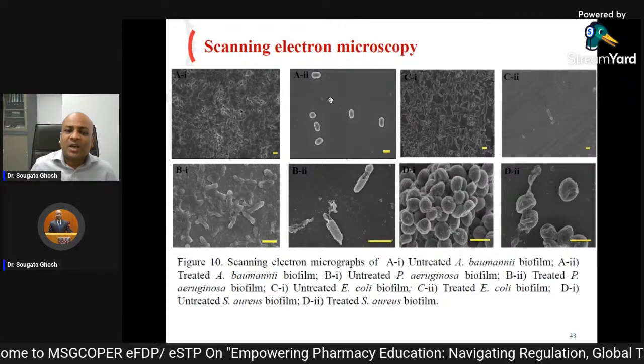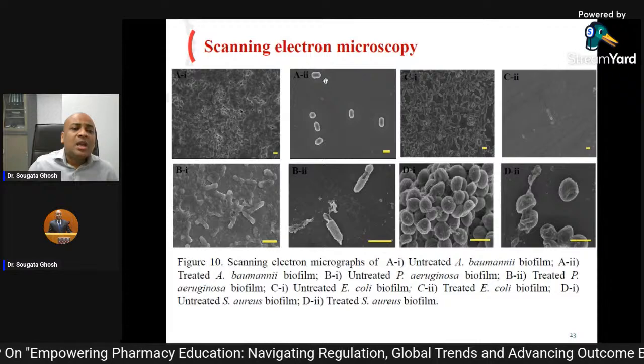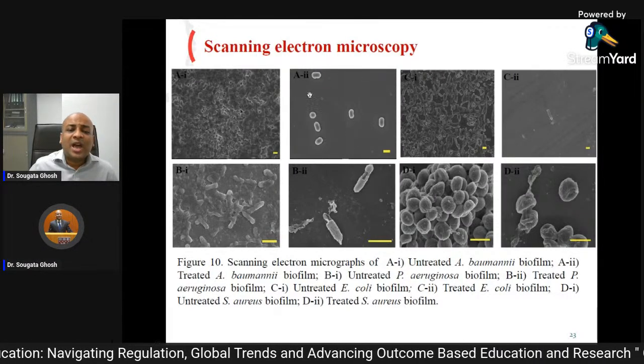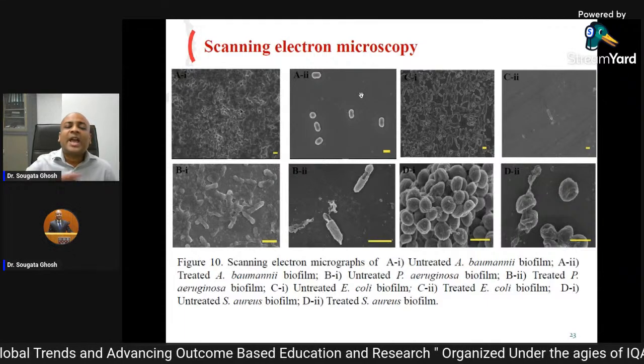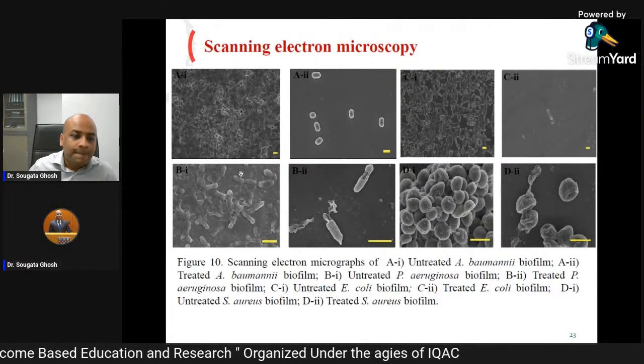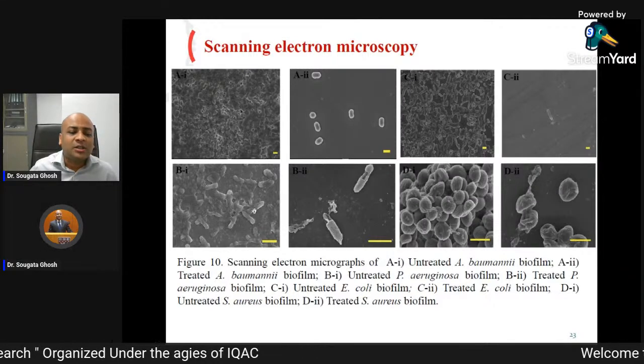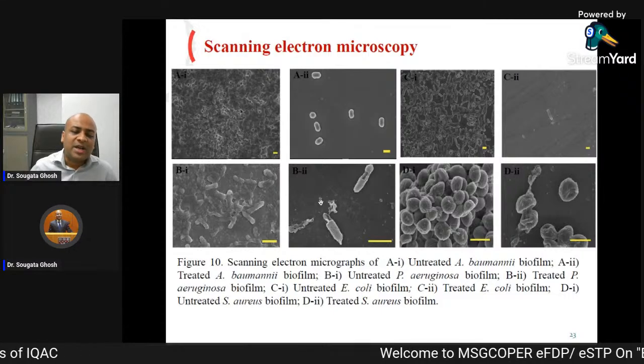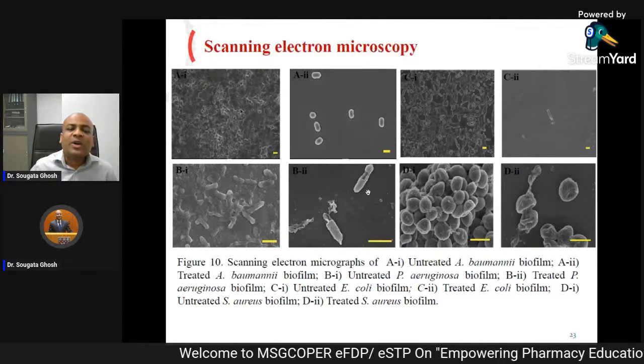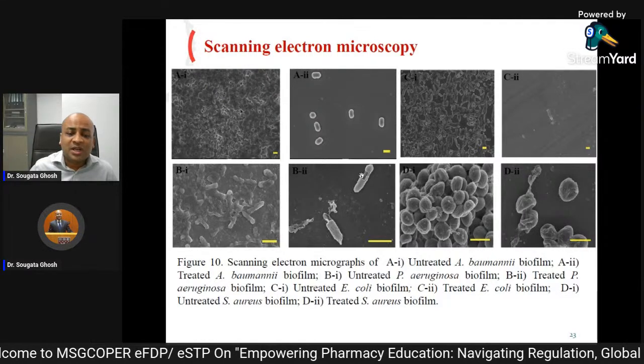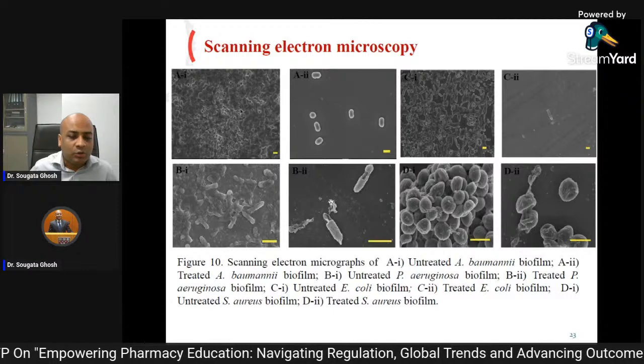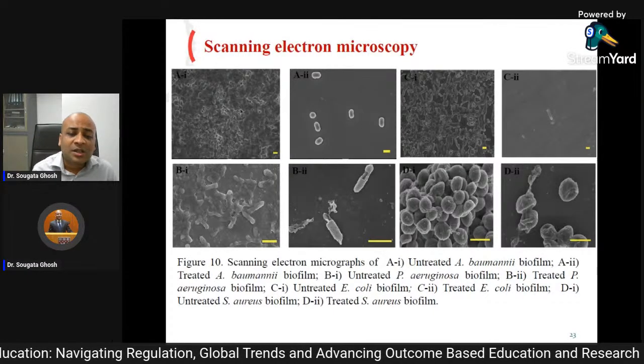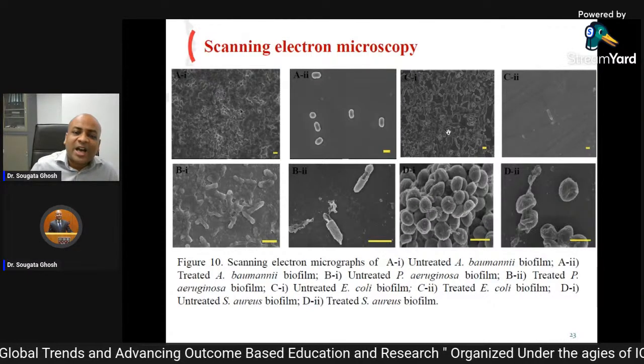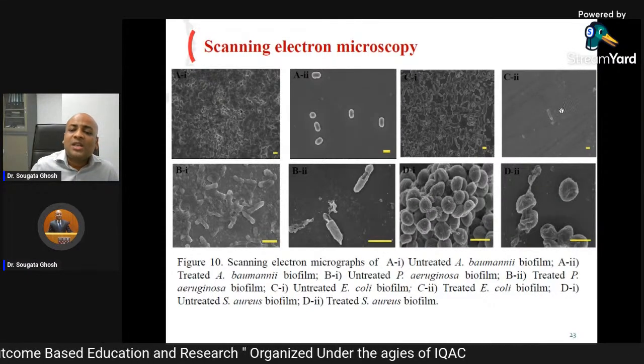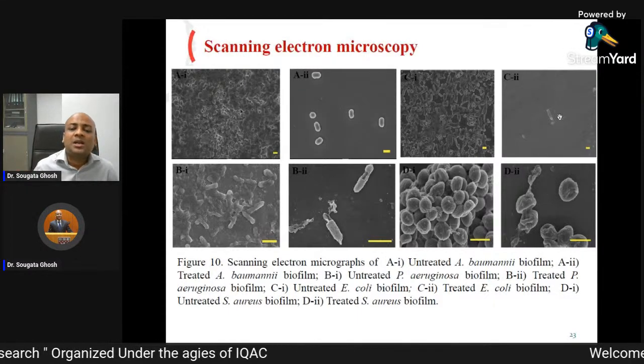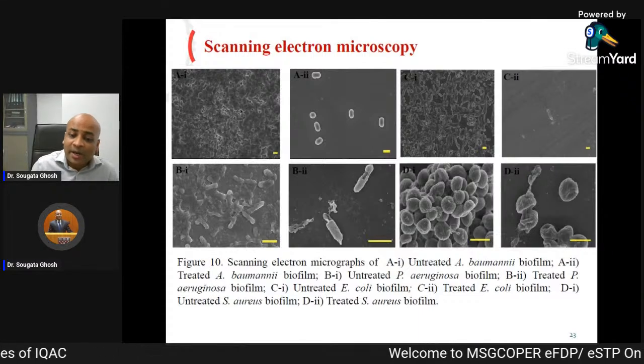As soon as we added our nanoparticle, within 48 hours, how many cells were there? Only 6 cells were alive on the substrate. The entire biofilm was removed, eradicated. In case of Pseudomonas, you can see a very intact Pseudomonas aeruginosa biofilm. When we treated with our gold core silver shell nanoparticle, you can see only 2 cells were left. Pore formation was there, cell wall degradation, and the inner contents were coming out. So, complete degradation of the Pseudomonas biofilm-forming cells. E. coli, intact biofilm over here in C. Only one E. coli cell was left after treatment. You can imagine how potent, how important, how significant this bimetallic nanoparticle is.